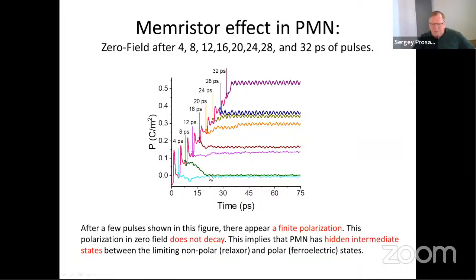So, for example, here it drops a little bit, but in other cases it stays longer at a constant value. So this is what we call hidden states. You see the difference? These are not intermediate states which appear dynamically, but rather states which in our calculations with bias fields we could not reach. We had a jump from a relaxor state under the bias field to the ferroelectric phase without any intermediate state. But here, by using these pulses, we can see these intermediate states having intermediate values of the polarization.